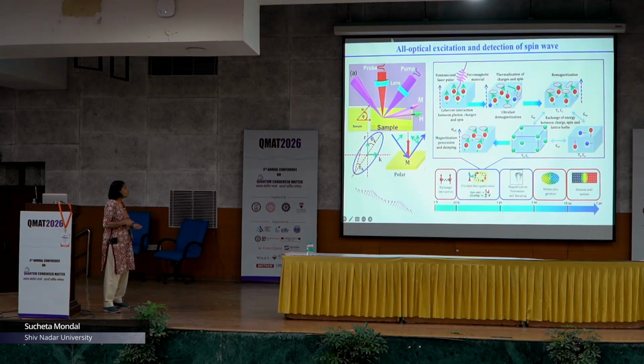Here is a summary of how we obtain precession or ultrafast demagnetization. So, let us say a collinear geometry is projected here, where the pump is hitting the sample and exciting the dynamics. The probe pulse is approaching normally, and we are obtaining polar MOKE signal in this geometry by saturating our magnetic sample, but giving it a slight tilt to induce precession later in time, which is a trick that we apply in the system.